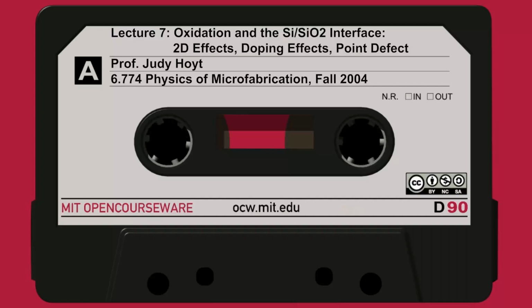But what do we know about highly doped regions from the homework that you did? When you increase the doping in a certain region, the total number of vacancies goes up, right? Because you move the Fermi level and you create charged vacancies, and you count up all the vacancies and they go up. Remember these equations you used on your homework that you're handing in today. If I'm intrinsic, my Fermi level is at mid-gap. I'm dominated by neutral vacancies. They have a certain concentration, 10 to the 13th or whatever.